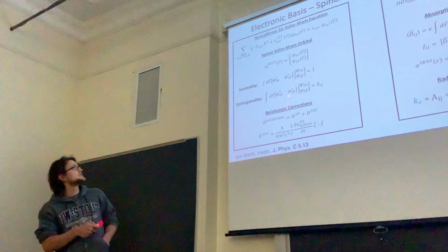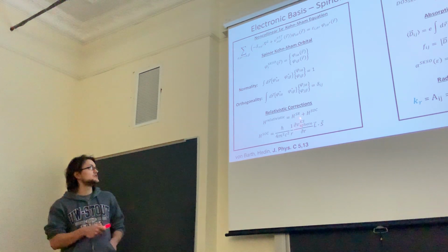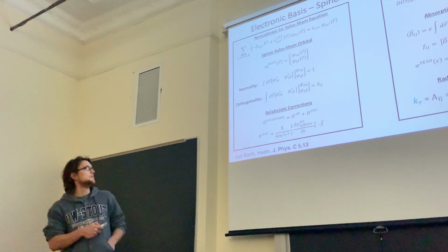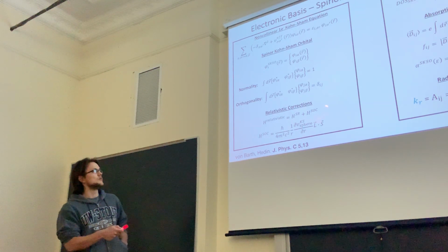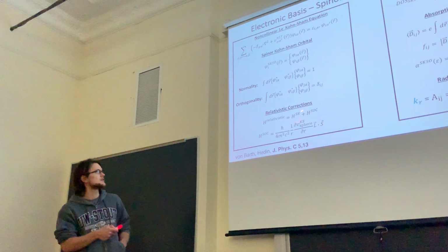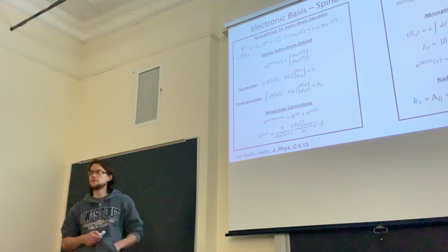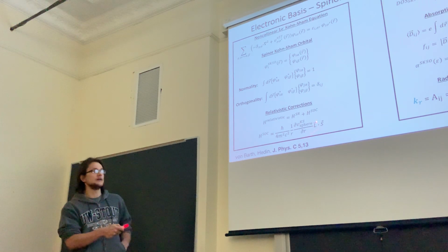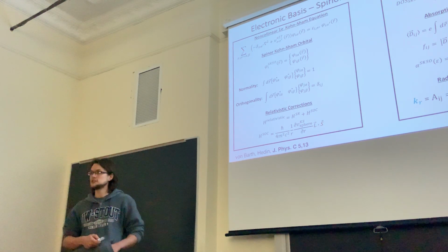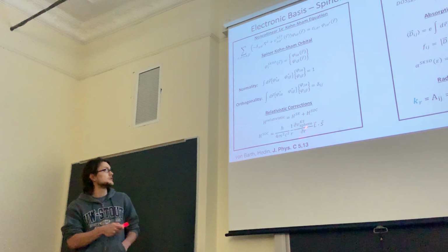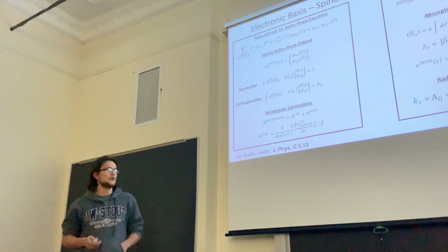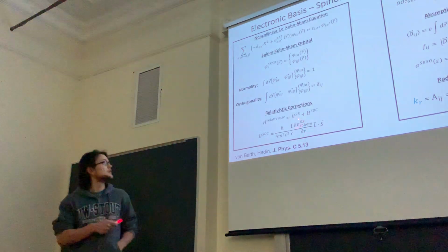The reason we have to use non-collinear orbitals is because perovskites have big relativistic effects due to lead orbitals that experience large spin-orbit coupling. Within the software that we use, they incorporate relativistic effects, so you have special relativistic effects and spin-orbit coupling. Spin-orbit coupling is the big one because lead has a very high angular momentum state, and that's what this L represents, the mixing of angular momentum with the intrinsic spin. That's why we have to use spinors, because the spin states are mixed. And this will have important consequences for the electronic states and kinetics in these materials.